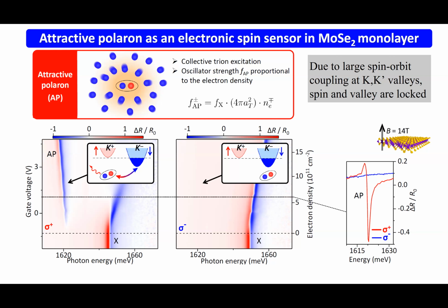So if I now generate an exciton in K plus valley, then just as advertised, I see this feature where I have the repulsive polaron and the attractive polaron showing up at low energies. But if, by using sigma minus polarized light, I generate my exciton in the same valley as the electrons, then I see this blue shift of the exciton, but there is no attractive polaron resonance associated with it. Okay, so this is very nice actually for our purposes if we want to study magnetization, because in this trivially magnetized case, you see that if I place all my electrons into this spin down state, so this is the spin valley locked state, if the electrons are all here, I can tell you that by just looking at the optical response. Right? When I see that I only see the attractive polaron in sigma plus, I can tell you that all the electrons are in the opposite valley.